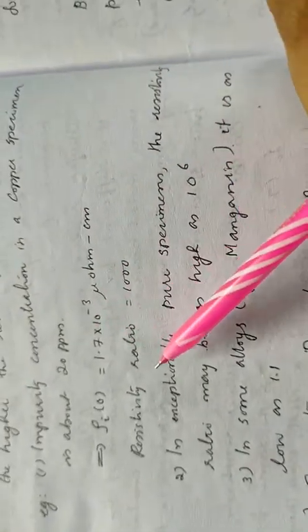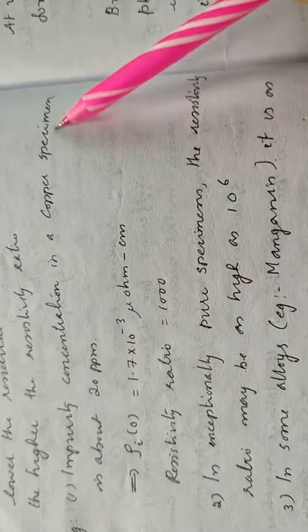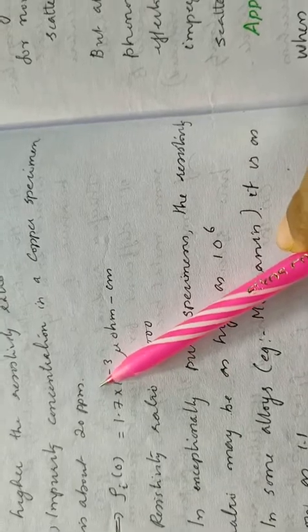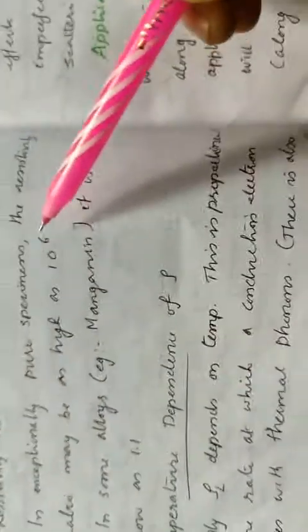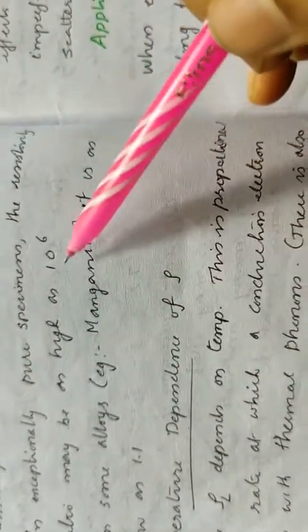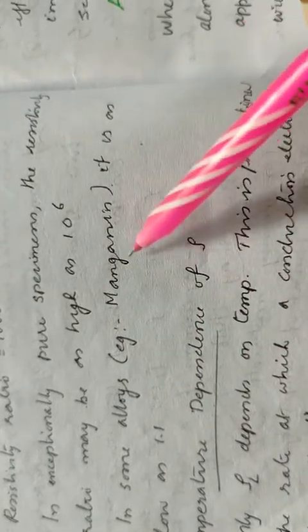Now, impurity concentration in a copper specimen is about 20 parts per million. This is an example. So rho I of 0 is 1.7 into 10 to the power minus 3 micro ohm centimeter. So the resistivity ratio will become 1000. In exceptionally pure specimens, the resistivity ratio may be as high as 10 to the power 6. In some alloys, like manganin, it is as low as 1.1.